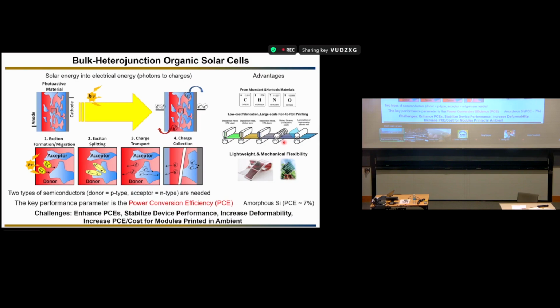In the bulk heterojunction organic solar cell, the photoactive layer has two components because the exciton cannot be split like in silicon or in other inorganics. It has a red phase, which is called donor, and a blue phase, which is called the acceptor. So it means basically you shine light on your photoactive layer, you form an exciton, which is an electron-hole pair. This pair migrates to the interface between the donor and the acceptor phase. The holes move in the donor phase, which is the p-type semiconductor, and the electron moves in the acceptor phase, which is the N-type semiconductor, and you have conversion of light into carrier.